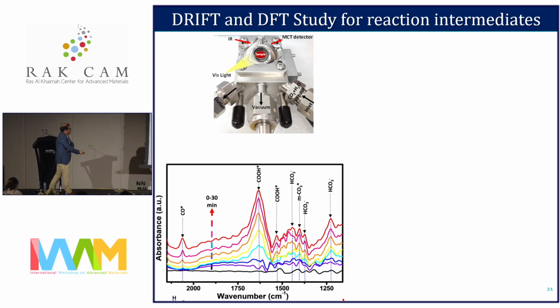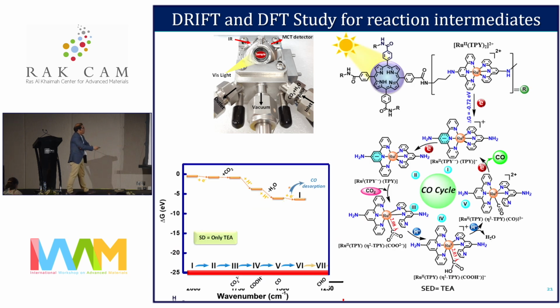We also performed the free energy calculation of this process. To understand the catalytic cycle: first this absorbs light, and electron and hole separate. These electrons go to the terpyridine site, and when the second electron binds there, there is an exergonic process. Then it goes to the second electron, ruthenium(2) becomes ruthenium(1), and eventually binds to CO2. One electron and one proton transfer during the COOH step, and removing water gives CO. So the whole process is exergonic.